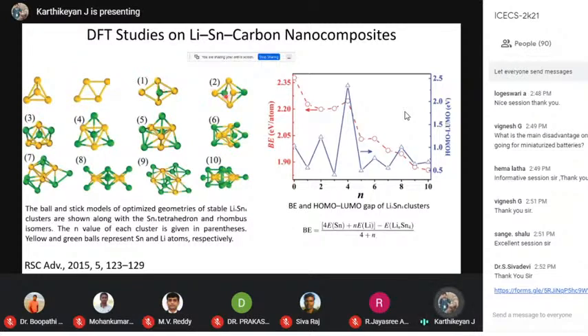When you increase the number of lithium atoms in this cluster, it turns into a tetrahedral shape. As you add more and more lithium, you can see that lithium-lithium bonds start forming, and the tetrahedral structure opens up. Initially it is a rhombus, slowly going to a tetrahedral-like shape, and if you add more and more lithium, it opens up again. It even breaks the tin bonds.